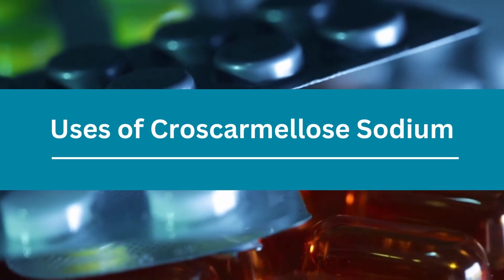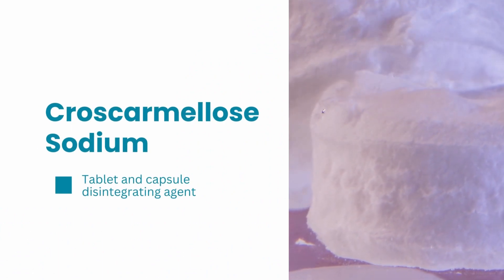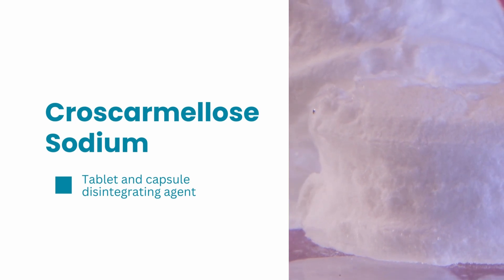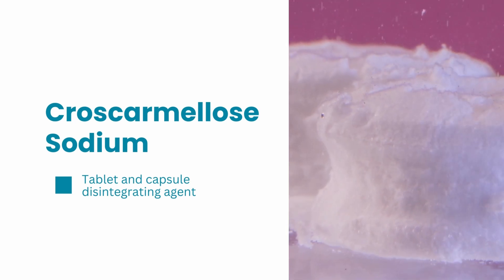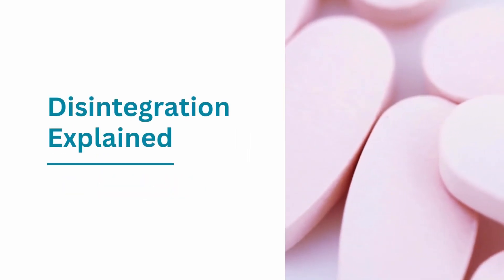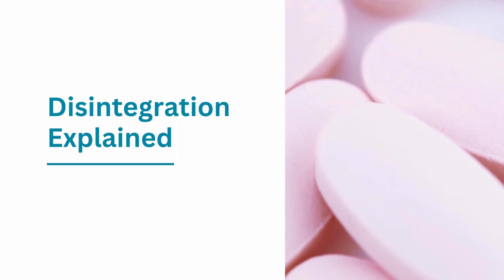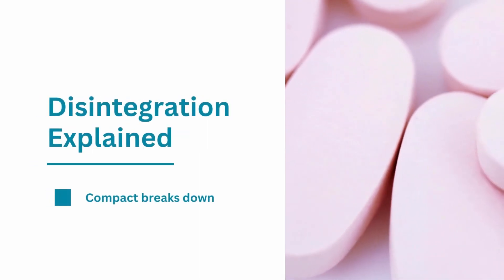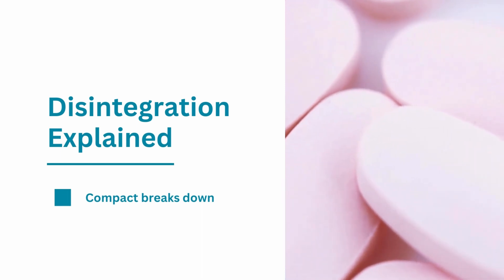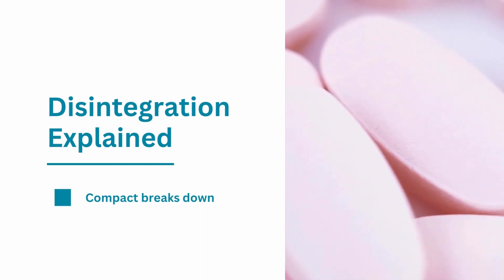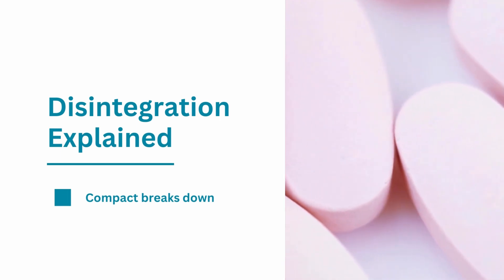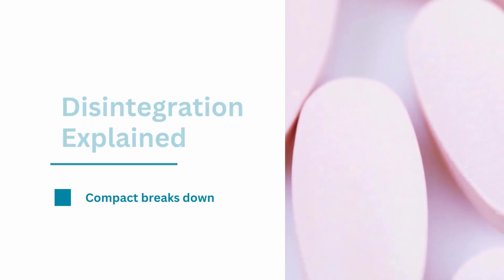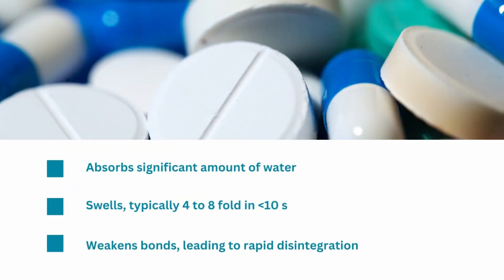The main and frankly only purpose of croscarmellose sodium is as a disintegrant in solid oral pharmaceutical products, both in capsule and tablet formulations. Disintegration is simply the process by which a solid tablet or capsule compact breaks down into smaller components in order to facilitate dissolution and absorption of the active substance. This is why disintegrating agents are important formulation ingredients. Croscarmellose sodium is capable of absorbing water rapidly, thereby swelling significantly — typically 4 to 8-fold — all in under 10 seconds. The action of pulling water into the tablet core reduces the physical bonding forces between the core's particles, which leads to rapid disintegration.